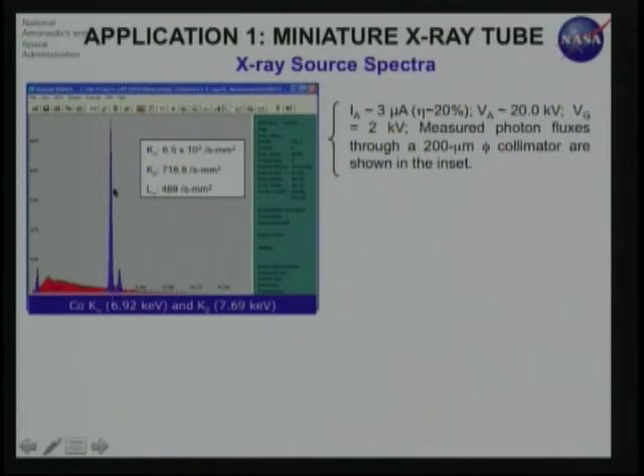These are the characteristic lines for cobalt: K alpha, which is 6.92 kilo electron volt, and K beta, which is 7.69 kilo electron volt. You have a pretty high flux at K alpha, about 6,500 photons per second per square millimeter, going through a collimator of 200 microns in diameter.